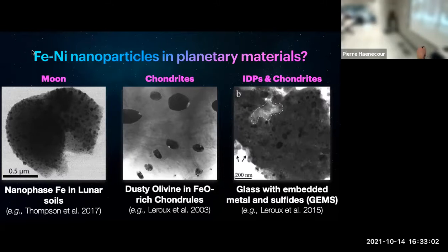We have also in carbonaceous chondrites those iron nickel particles observed in a particular type of sample we call chondrules, in particular here in dusty olivine in chondrules. Chondrules are those spherical beads of glass that you can find in carbonaceous chondrites. That's where the name chondrites comes from, because they all contain those chondrules that we know formed by some kind of flash event that melted dust really quickly, and then that dust condensed into either a mixture of glass and silicates. Some of those silicates, here you can see olivine grains, show these nanophase particles included in them as inclusions.